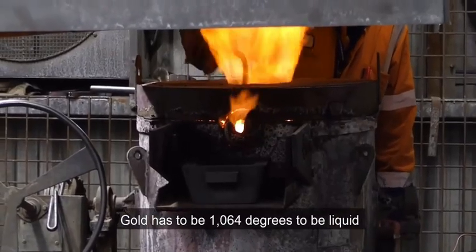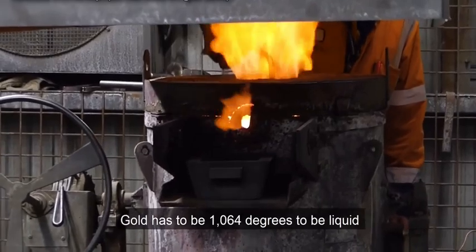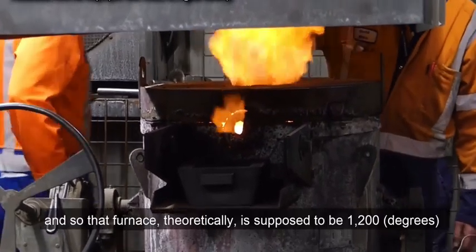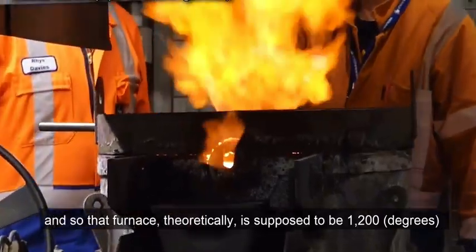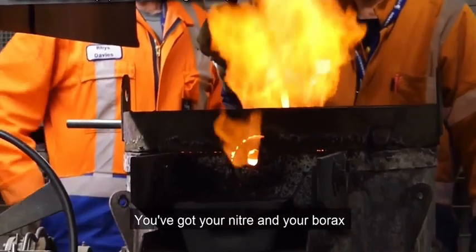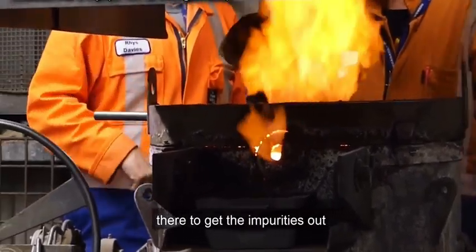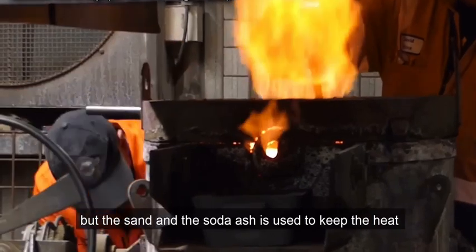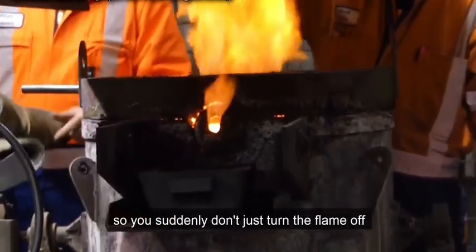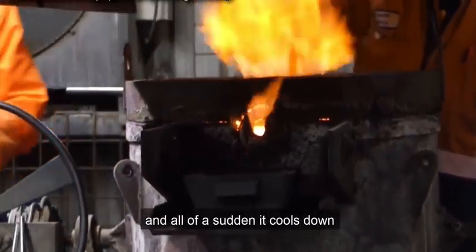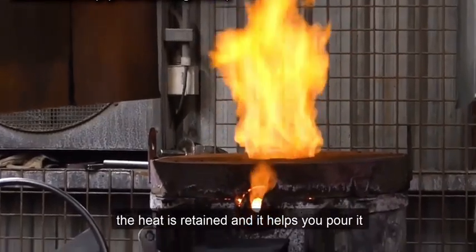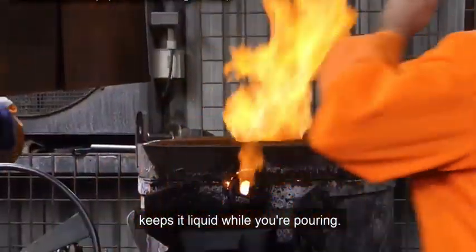Gold has to be 1064 degrees to be liquid, and so that furnace, theoretically, is supposed to be 1200 degrees. You have got your niter and your borax there to get the impurities out, but the sand and the soda ash is used to keep the heat. So you don't just turn the flame off and all of a sudden it cools down. The heat is retained, and it helps you pour, it keeps it liquid while you are pouring.